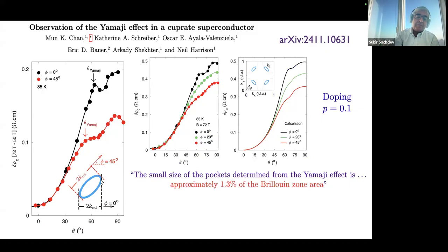And so they assume some elliptical Fermi surface, presumably there's 4 of them for different reasons. And they concluded that each such area pocket encloses 1.3% of the area of the Brillouin zone, which is this. Okay, so just remember that 1.3%. So that is, I claim, a key clue to the nature of the state of these materials and its quantum entanglement.